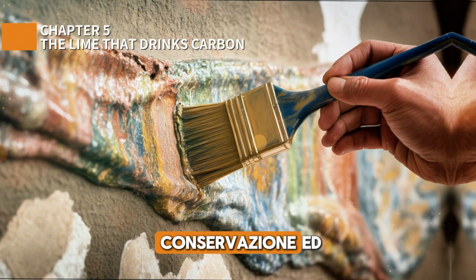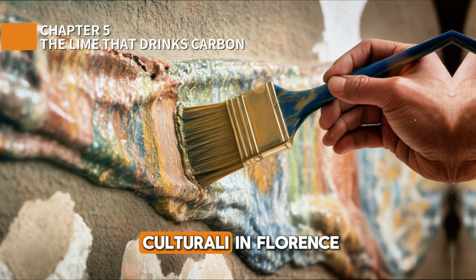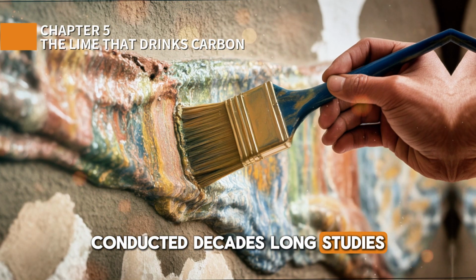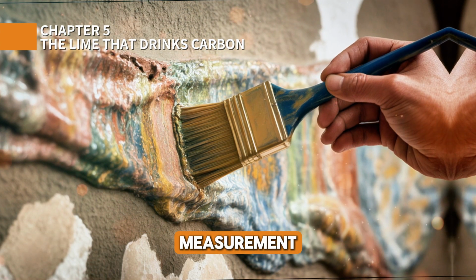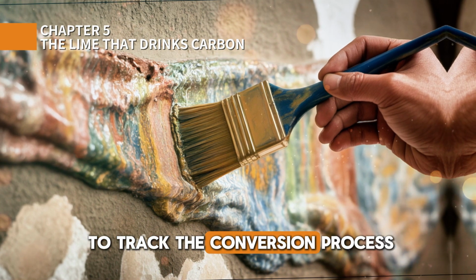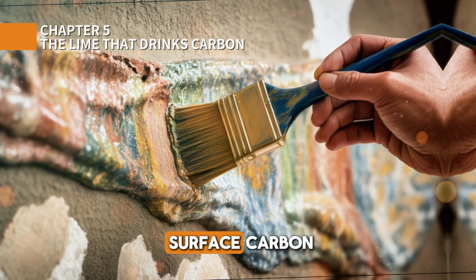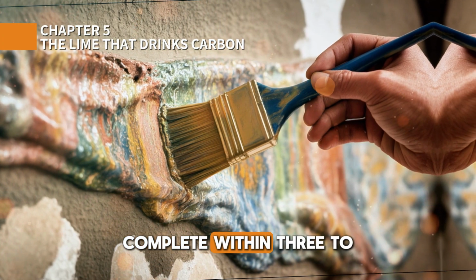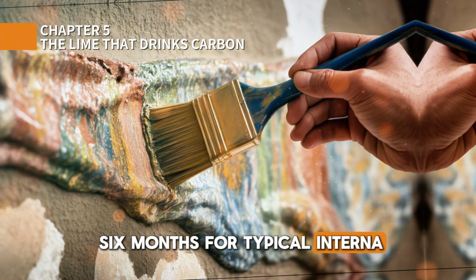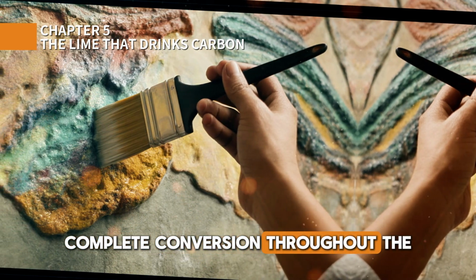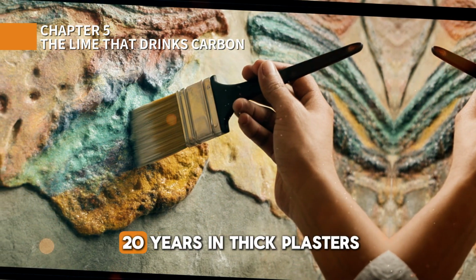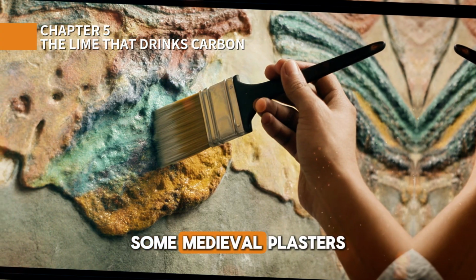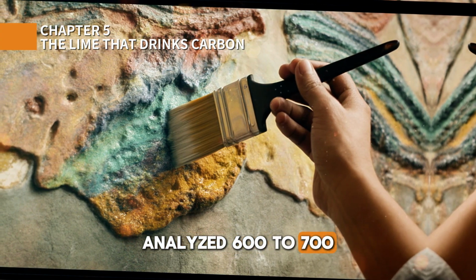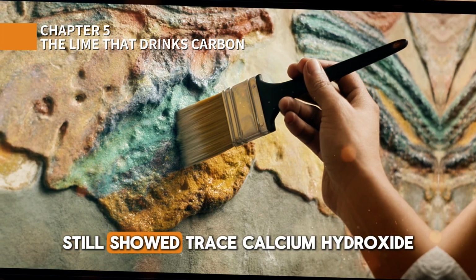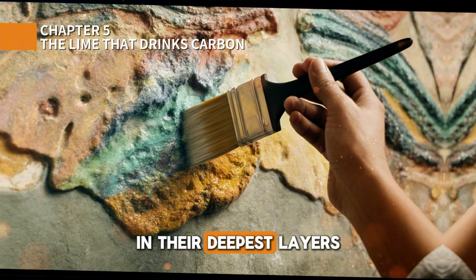The Centro per la Conservazione ed il Restauro dei Beni Culturali in Florence conducted decades-long studies of fresco carbonation, using pH measurement and X-ray diffraction to track the conversion process. Their findings showed that surface carbonation is essentially complete within 3 to 6 months for typical intonaco thickness of 5 to 8 millimeters. But deep carbonation, complete conversion throughout the plaster thickness, continues for 10 to 20 years in thick plasters. Some medieval plasters, analyzed 600 to 700 years after application, still showed trace calcium hydroxide in their deepest layers.